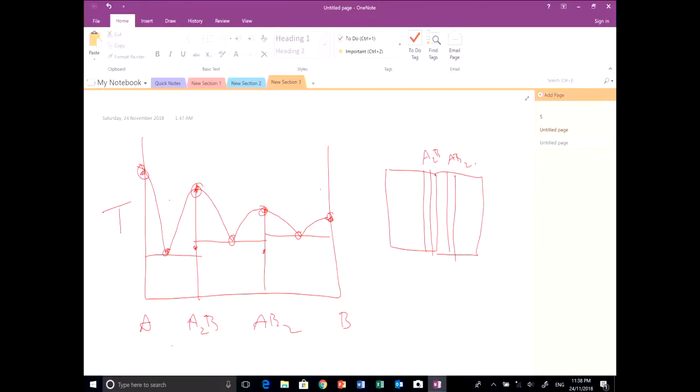And they're actually located in the middle of the diagram because diffusion has to go one way and then the other way for the other element, and as they cross, they react, and they form these phases. So you'd actually be able to draw a phase diagram just from the microstructure. And we still use that principle when we analyze microstructures, when we're trying to figure out what happened to a material that's gone bad or good or whatever. All right, so we have lots of possibilities here for intermediate phases, and there are systems with 6, 7 compounds that can form.